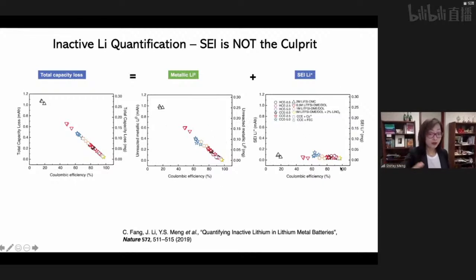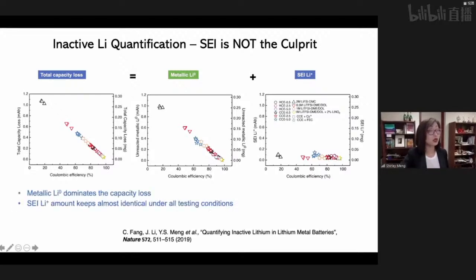I want to emphasize here that, of course, some of these Coulombic efficiency numbers are so bad because we deliberately chose an electrolyte that gave very bad Coulombic efficiency to prove the point. So when people are now working on high efficiency electrolytes, I want to emphasize the SEI is still very important, right? This work is already 2 years old, to showcase that first we need to understand and control the microstructure of the lithium metal, and the SEI is not the main reason for the low Coulombic efficiency of lithium metal batteries.